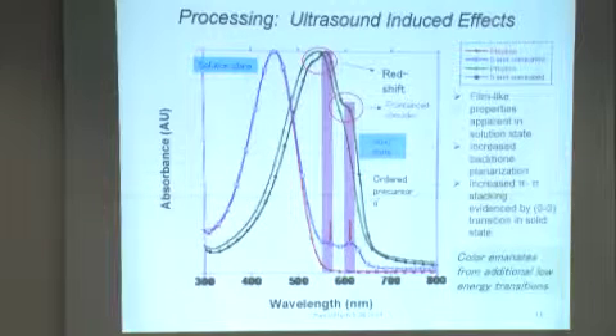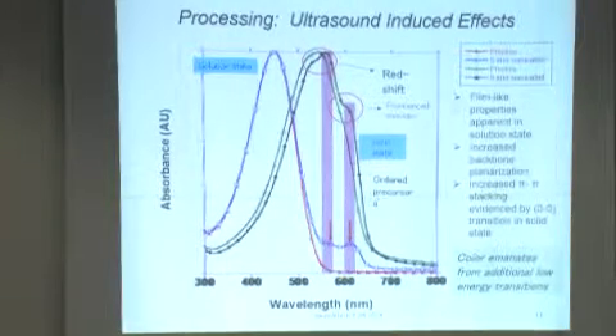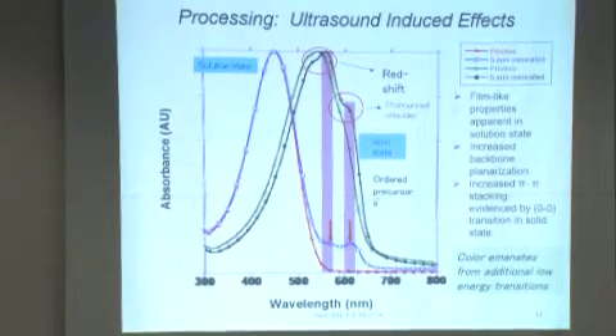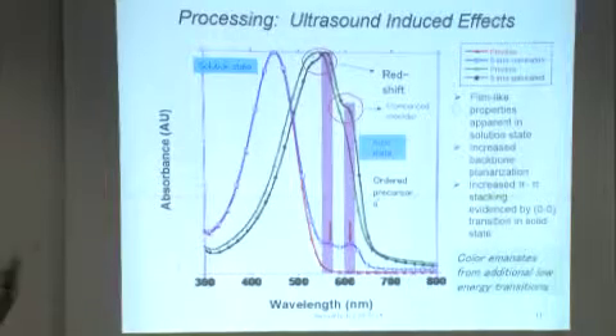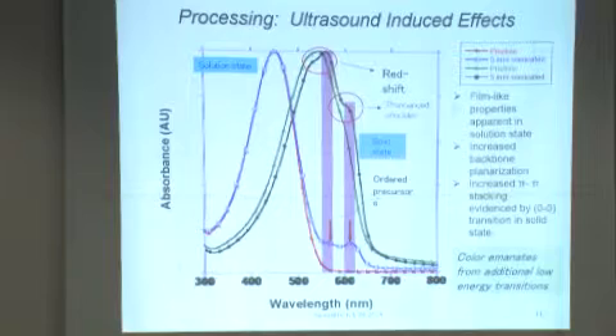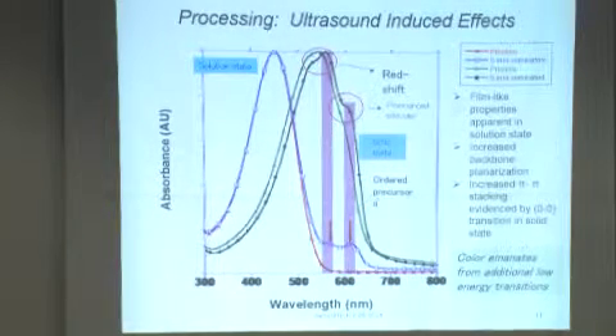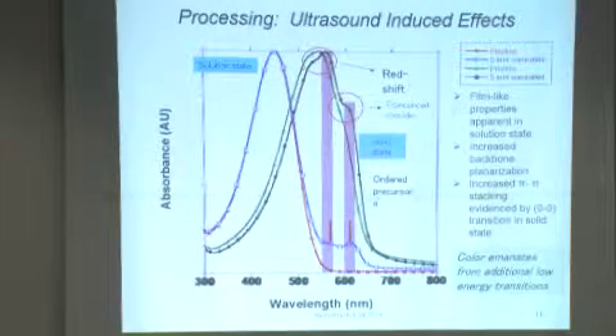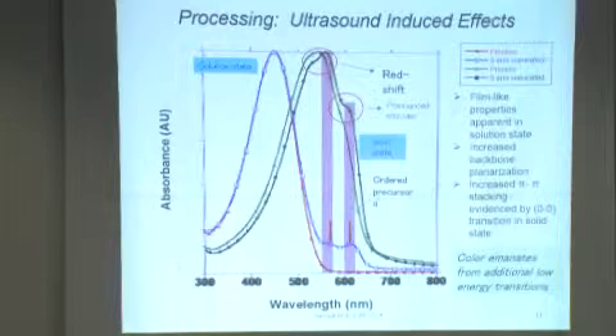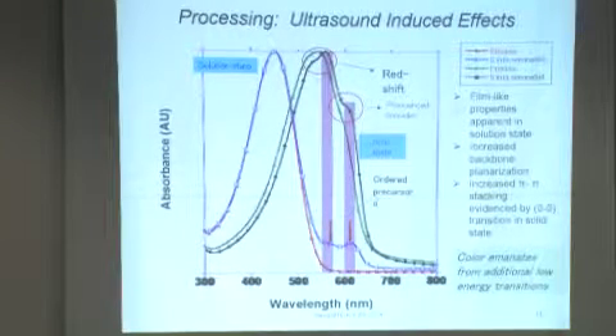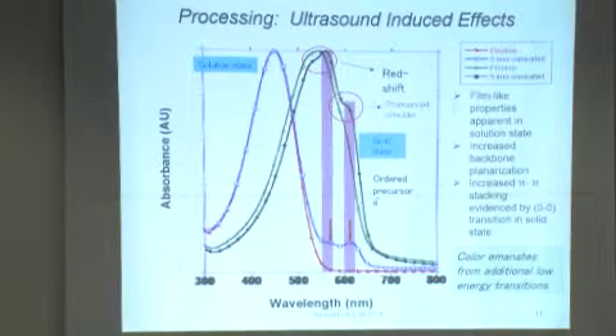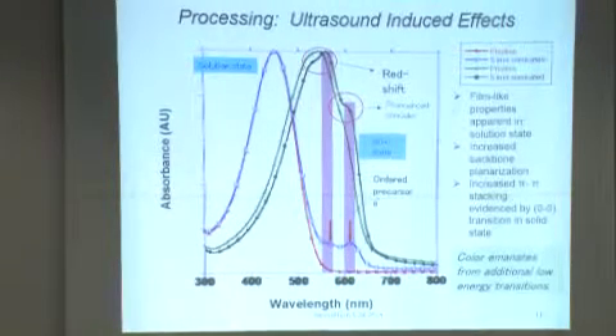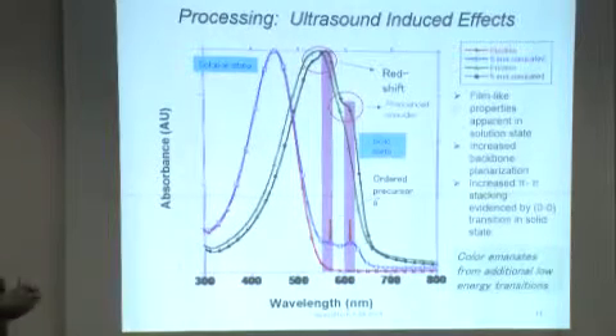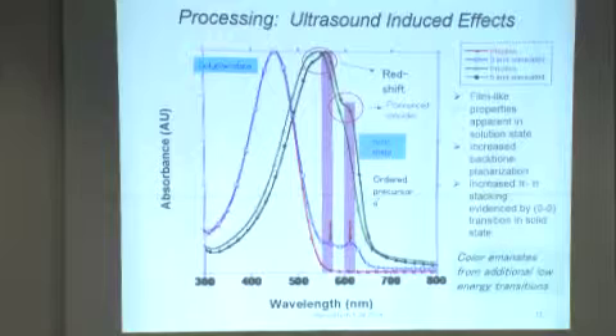All right, so Avi went back and repeated the experiments, did a lot of photophysical studies, did some very critical control experiments, because what he noticed was he could take an orange solution of poly-3-hexylthiophene in chloroform, ultrasonicate it, it turns sort of dark purply black, and then he could take that purply black solution, heat it very mildly to 50 degrees, and it goes back to this nice orange clear solution. So whatever was happening was reversible. And we did all the characterization to show that yes, indeed, that process is reversible. So we're not doing anything chemically to the polymer itself.